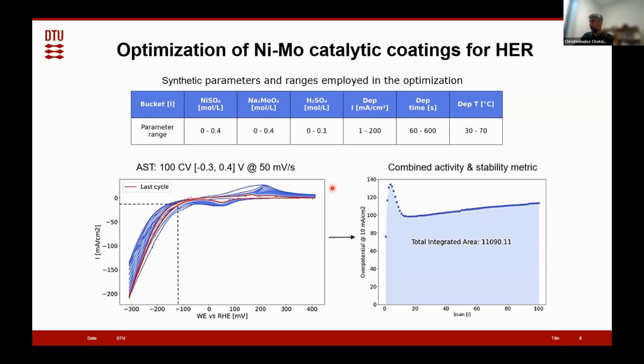And the way we qualified the performance of the electrode was again by doing 100 CV cycles between cathodic potentials and 0.4 volt anodic potential at 50 millivolts per second, and then analyzing the results with respect to the overpotential at -10 milliamp per square centimeter over these 100 cycles, and taking the total integrated area below this overpotential. Basically, the average overpotential over these 100 cycles as a combined metric for both the activity of the coating and the stability of the coating under cycling in this potential window.